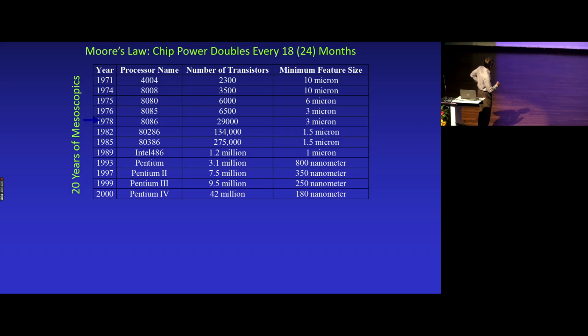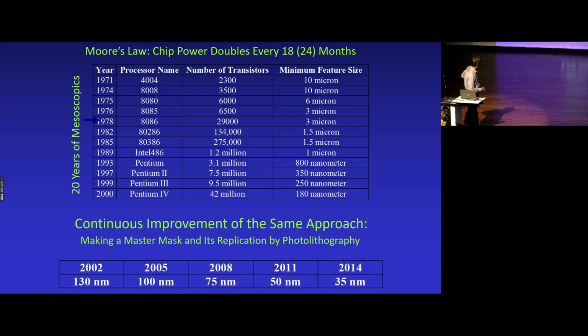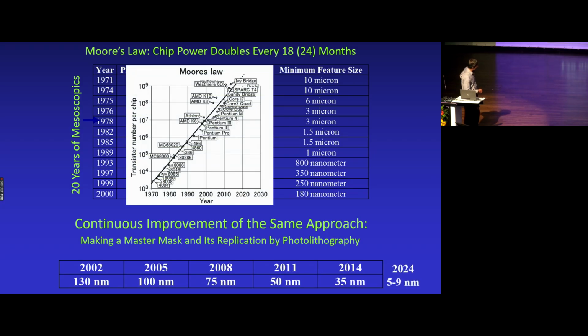For example, when we started our studies around 1971, 1974, the smallest transistor that you could make was 10 micron. 10 micron is really very small. It's 0.01 millimeter in size. And you could pack in 3,500 of those transistors to make one CPU, or processor, that was called the 8008. You can see how the transistor size kept decreasing over the years, coming down to 180 nanometers by 2000. And by 2014, starting from 10 micron, it's at 35 nanometers. In fact, today the size of the transistors is down to 5 to 9 nanometers. And you are packing in billions of them. And that is why computer power is going up so fast.